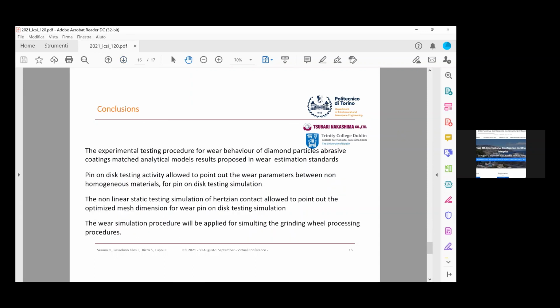In conclusion, we can say that the experimental procedure for the wear behavior of diamond abrasive coatings matches the analytical models in the wear estimation standards. Pin on disc tests allowed us to point out the wear parameters of non-homogeneous materials. Then the mesh optimization of the wear pin on disc simulation was pointed out thanks to the nonlinear static testing simulation of the contact. Lastly, the wear simulation procedure will be applied for simulating the entire grinding wheel processing procedure.